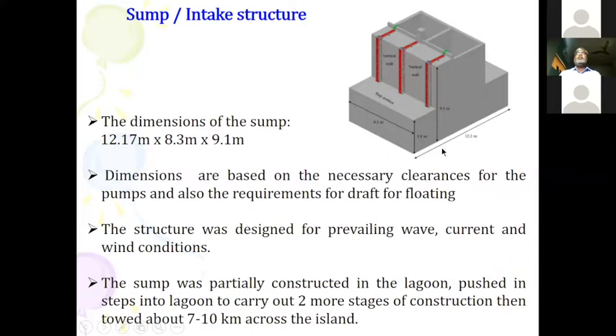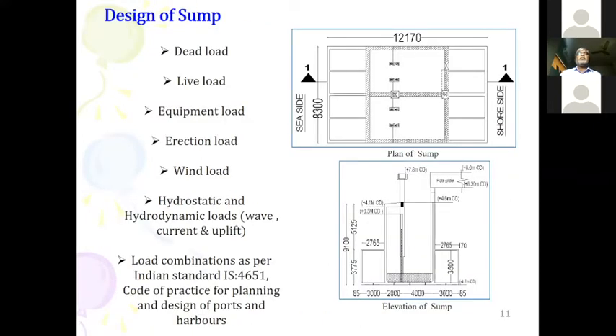The dimensions of the sump, if you look at it, the floating foundation which you are going to make at the bottom is going to be about 12.17 meter by 8.3 by 9.1. Because as I said, during peak monsoon you'll have about 9 meters of wave height, and in pre-monsoon you'll have 5 meters. So 9.1 is what we have designed for the sump foundation. Over it you will have a 2-compartment sump, which will be watertight, of course, with 2 electrical motors for drawing the water, which is actually an intake structure. Otherwise, you can call it a sump.